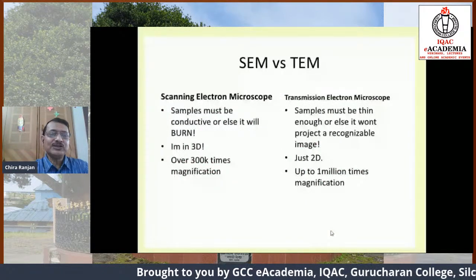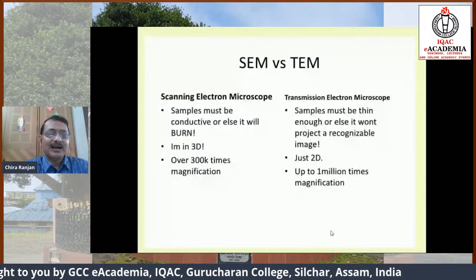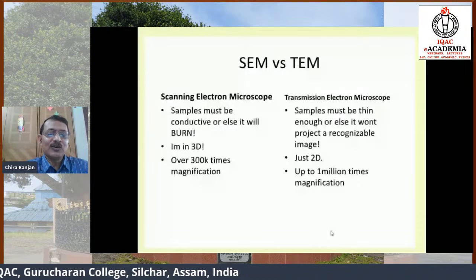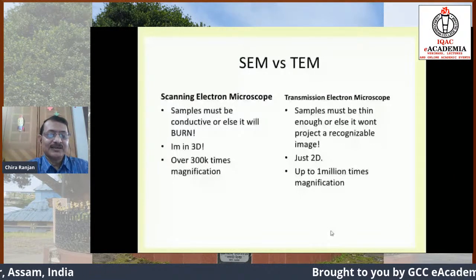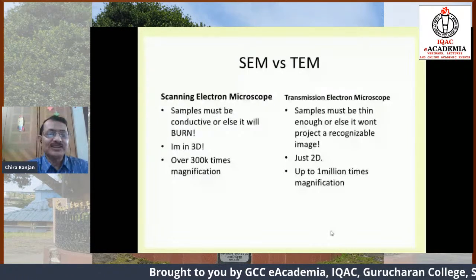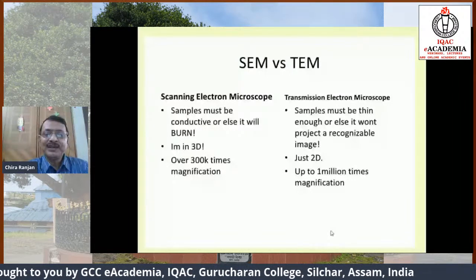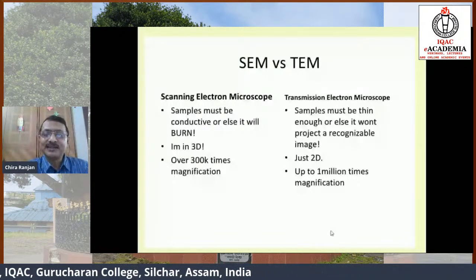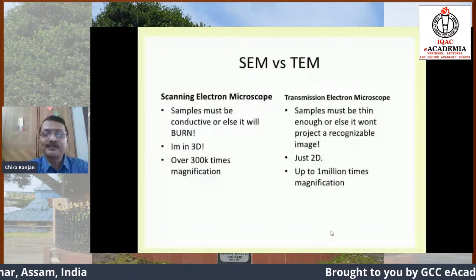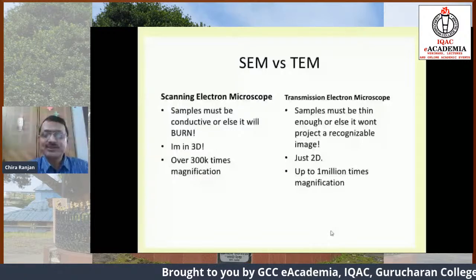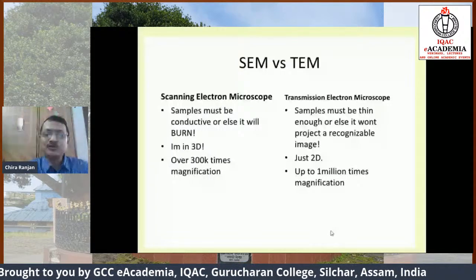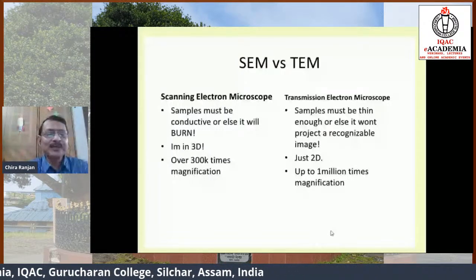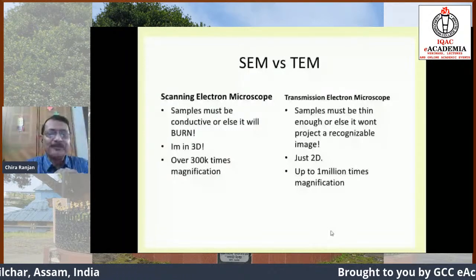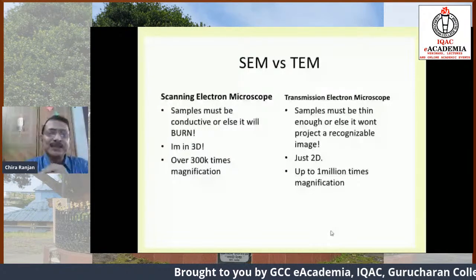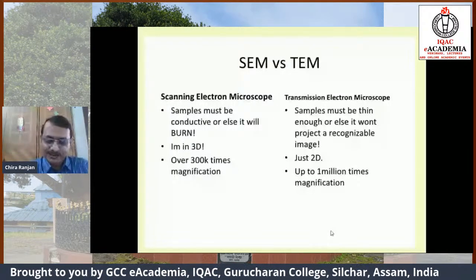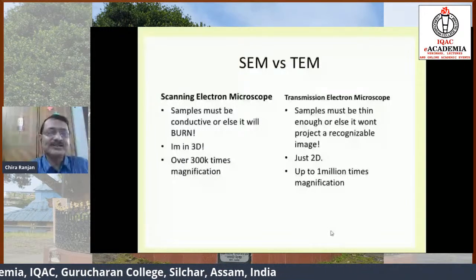So basically, if we would like to put SEM versus TEM, for SEM, the sample must be conductive or else it will burn. Over 300,000 times magnification may be possible in a scanning electron microscope. In a transmission electron microscope, the sample must be very, very thin, else it won't project a recognizable image. It is just two-dimensional, and magnification can be achieved up to 1 million times in TEM. So these are some pros and cons of using SEM and TEM, but depending on a given sample type, both techniques can be very useful, with certain merits and demerits.